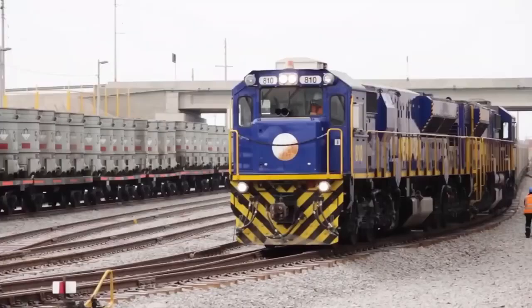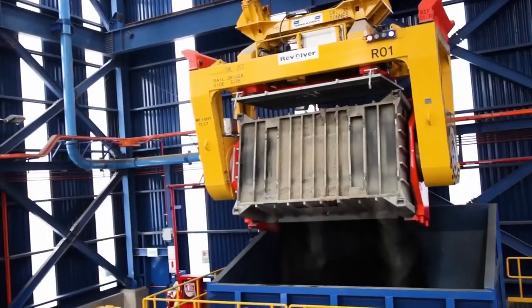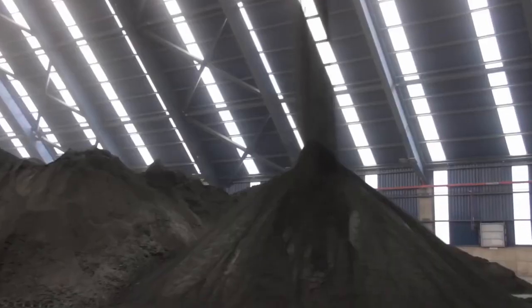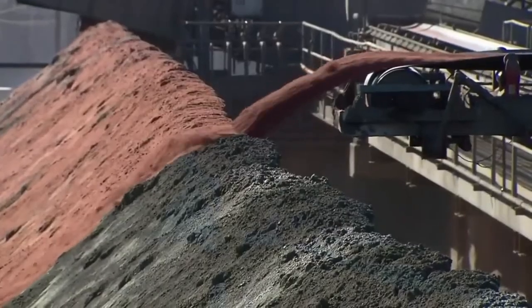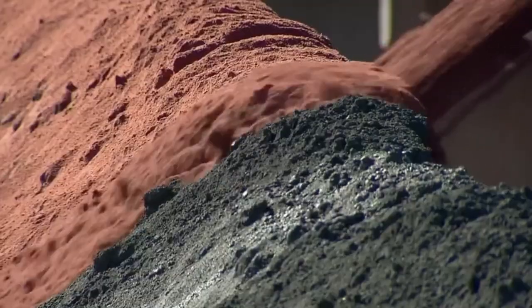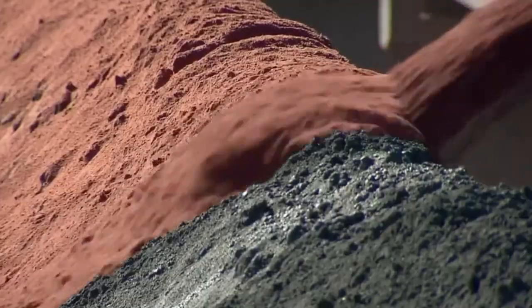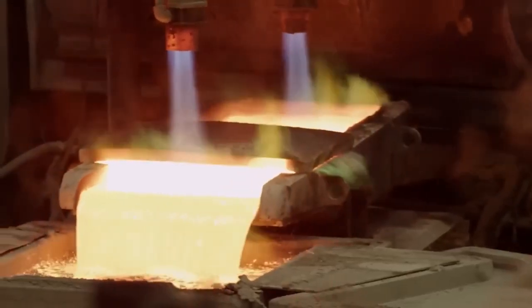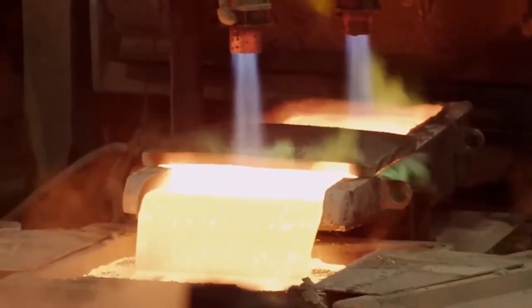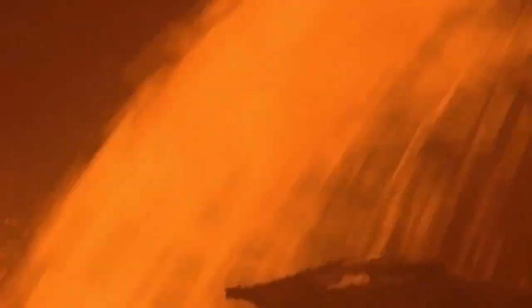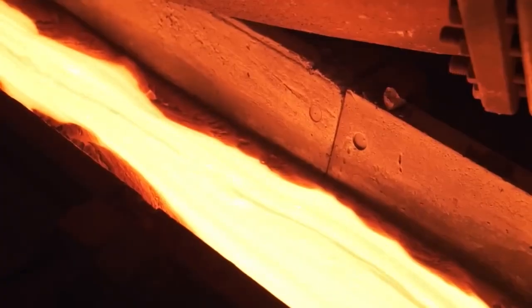The concentrate travels by train to huge yards, where it is layered with silica sand known as flux. This sand helps remove impurities during smelting at extreme temperatures. The mixture turns into a molten liquid, with slag made of iron and other minerals floating while copper sinks. At this point, it reaches 60% purity. It then passes to a second furnace, raising the copper content to 98%.